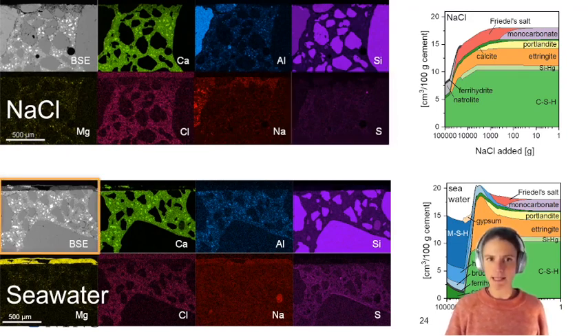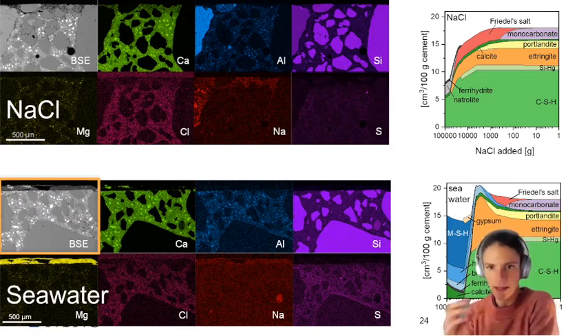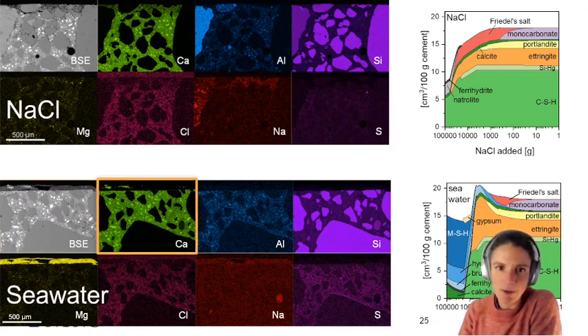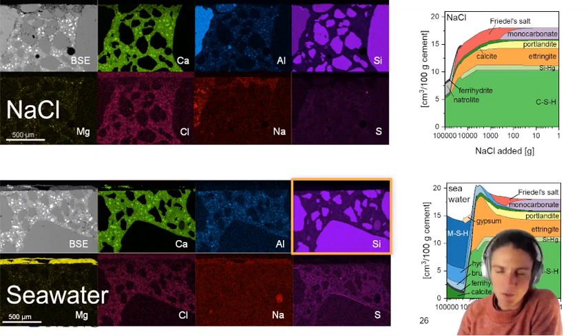So if you look at the BSE image, we don't have this darkening of the cement paste towards the exposed surface. So we don't have the same extent of leaching or dissolution of our cement paste. On the top, we have some dark gray matter, and when we look at the elemental maps, we can see what this is. So when we look at calcium, we see that we have something drizzled on the surface. That's calcium carbonate forming at the surface. And also see a lot of calcium in the cement paste, but not really the clear leaching as we saw for sodium chloride. Jump over aluminium, not that interesting here.